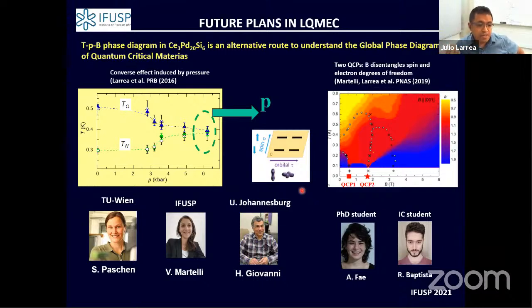In addition, what we have seen here is just a problem with the quantum phase transition involving spin degrees of freedom, but the physics can be even more complex if you add the electron degrees of freedom, like for instance in a heavy fermion system such as cerium-3 palladium-20 silicon-6, offering another type of degrees of freedom, that is the orbital degrees of freedom, right? So this previous measurement under magnetic field in this heavy fermion showed that by the application of the magnetic field, you disentangle each of these degrees of freedom in two different quantum critical points.